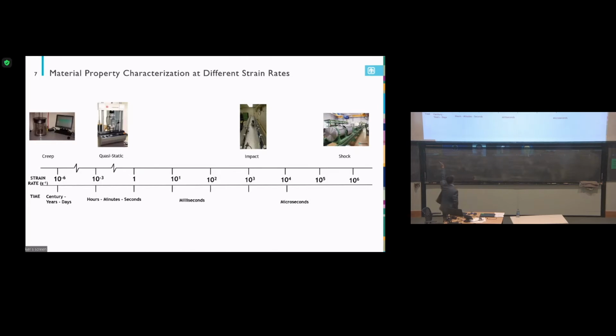Of course, lower than that, there's creep. It's extremely low. We're not going to talk about this, but generally we start with quasi-static. Quasi-static is a strain rate like 10 to the minus 3 or 10 to the minus 4 up to 1 per second. Higher than that, that's what we call the impact. That's on the order of 1,000. You can see that's 1 million times higher than the quasi-static test. Now above that, that's what we call the shock.